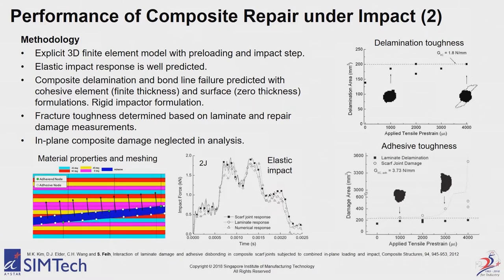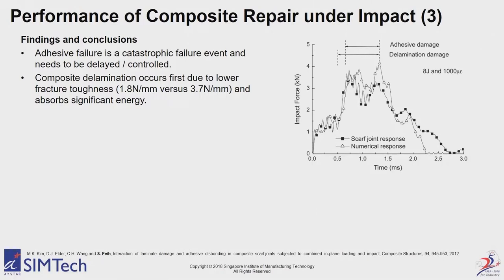And from that, we actually did some little mind games. And we said, OK, what happens first? Adhesive damage or delamination damage? OK, first the composite is damaged because its fracture toughness is lower. That's interesting, because if the composite damages first, that's non-catastrophic. Adhesive damage is actually fairly catastrophic. So to some extent, the composite takes up energy that would otherwise damage the adhesive layer.